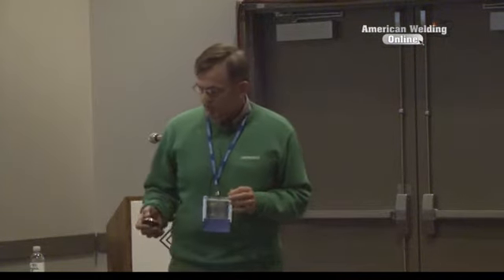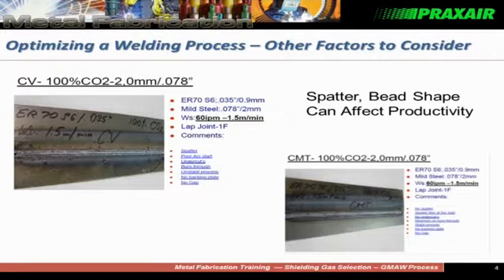The photo, this is a little bit hard to see from a distance, but here we're talking about using a conventional welding supply with 100% CO2 shielding. This is a lap fillet weld. What you can't see too easily here is that there's a fair amount of spatter along the edges of the weld. The edge of the weld is kind of crowned, so if you needed a smooth flat surface, it might require some grinding. Here, a different type of process, a controlled metal transfer process, virtually a spatterless process, a flat weld bead. So again, a little bit less post-weld processing would affect this operation.